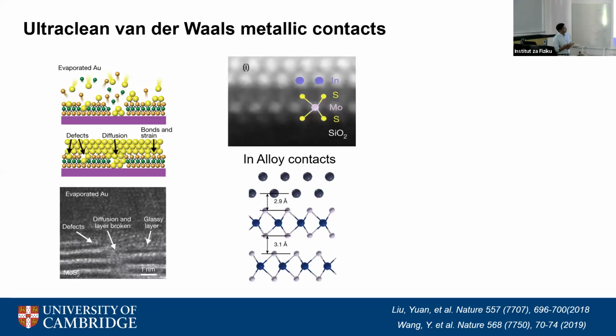Manisha's group, when I joined the group, was pioneering a technique which showed that you can make van der Waals contacts. Now, what do we mean by van der Waals contacts? It means that if you choose a metal with a very low melting point, like indium, you can evaporate it very easily. And when it evaporates, it has very low kinetic energy, and it can form a very clean interface with the molybdenum sulfide. And why do we call it van der Waals? We were asked this question a lot of times: why do we call it a van der Waals contact?